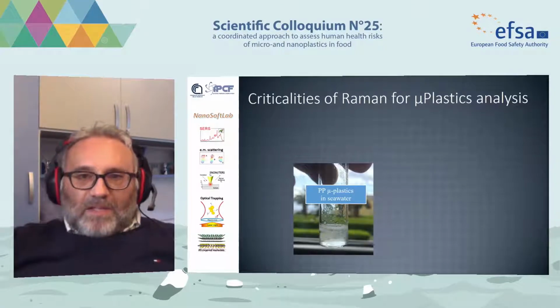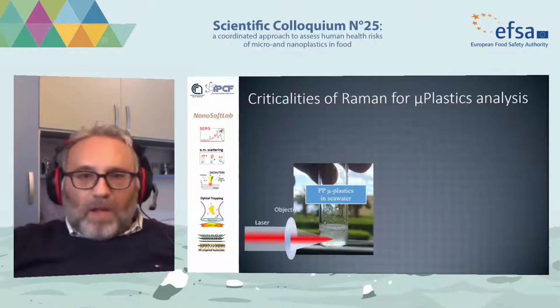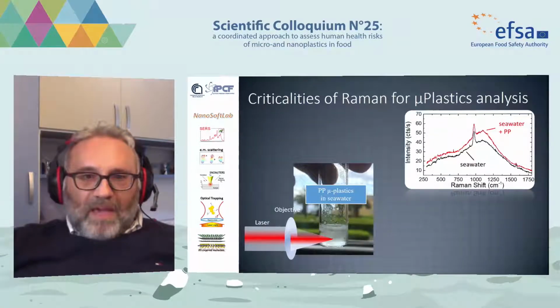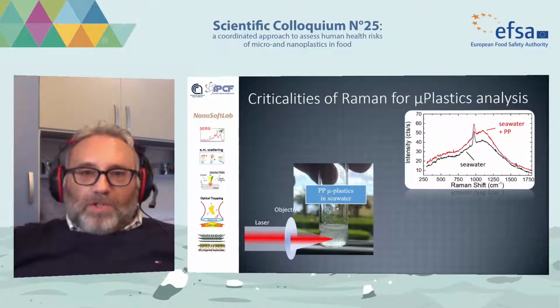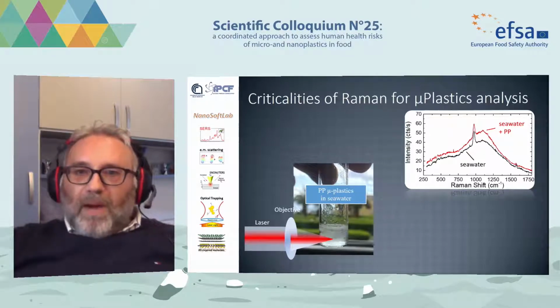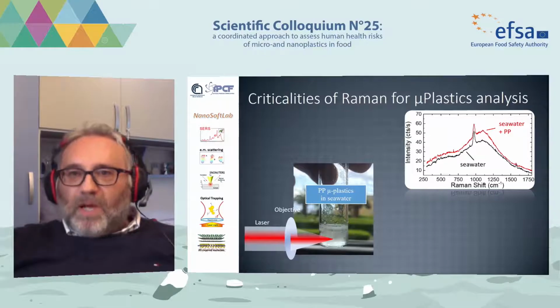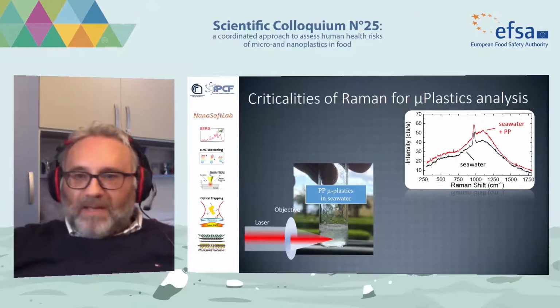As you see here in this cuvette, we have a dispersion of polypropylene microplastics in seawater. Interestingly, if we measure this solution and compare it to the same solution without the polypropylene particles, we basically see the same spectra. The red and black lines are basically the same.